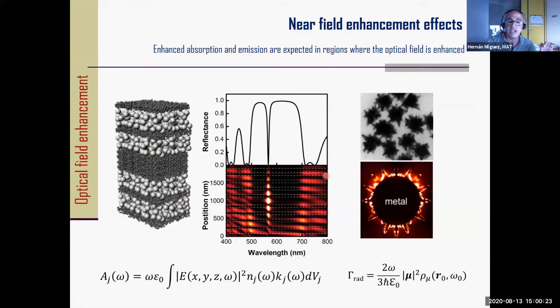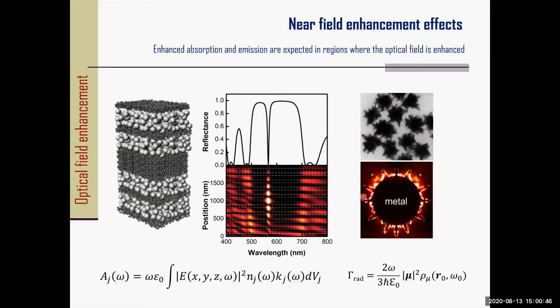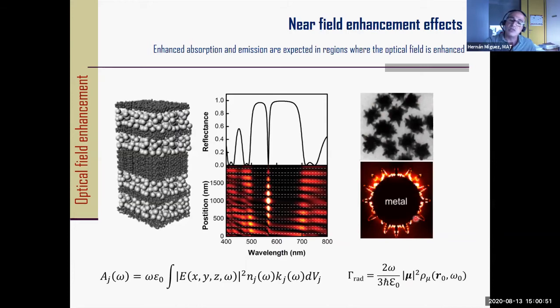So these are the layers. This would be the depth in the structure, and certain wavelengths. You can get very intense light field enhancements, right? And a similar thing happens when you use metallic nanoparticles. I chose these gold nanostars as an example, and this is also a simulation, and you can clearly see how when you illuminate them, light intensity is going to be enhanced around the nanoparticle.